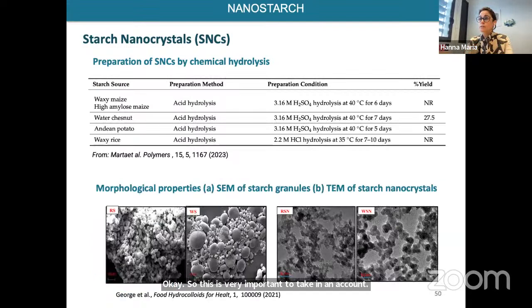So to prepare the starch nanocrystals by acid hydrolysis, we need to take into account different factors: the starch concentration, the acid concentration and type for sure, the time of the agitation and the temperature, and also the kind of agitation or the number of rotations per minute. Okay, so this is very important to take into account to do your chemical hydrolysis.